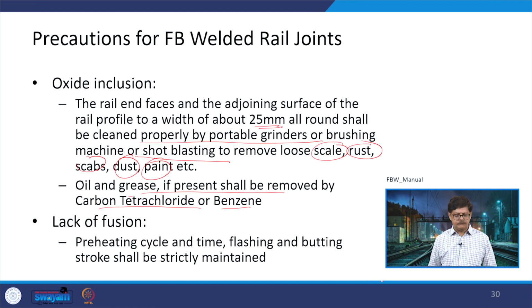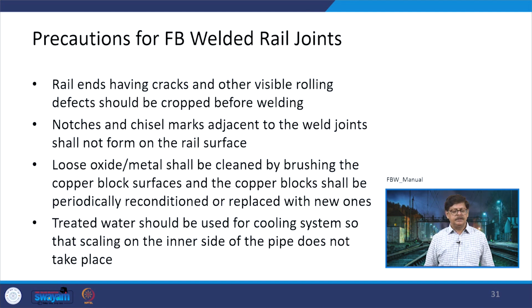In the case of lack of fusion, the preheating cycle and time, flashing and butting strokes need to be strictly maintained. Otherwise, the fusion of the two rails will not be there. Then the rail ends having cracks and other visible rolling defects should be cropped before welding. So, this we have already talked about. Another precaution is notches and chisel marks: if they are there adjacent to the point where the welding is to be done, then they again have to be removed.